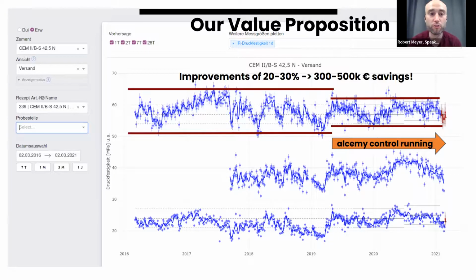So usually that amounts to savings on the order of 300,000 to €500,000, a mixture of different things. It could be savings on grinding energy. It could be savings on actual CO2 certificates, because now I can really reduce the clinker even within the cement standard that I currently have, and just counteract with more fine grinding. Or because I have a better quality cement, I usually can also charge a bit more to my customers.